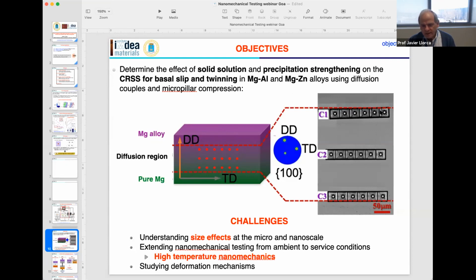These micropillars here will have a composition that is C1. These micropillars here will have a composition that is C2. And these micropillars here will have a composition that is C3. And then by testing these micropillars, you are able to measure the critical resolved shear stress for different deformation modes. Of course, this will depend on the orientation of the micropillars, so you have to do this in grains with different orientation. This is the basic objective.